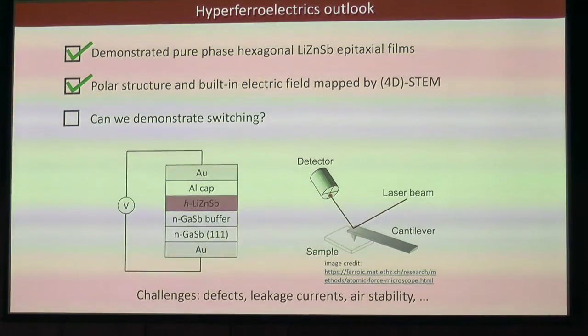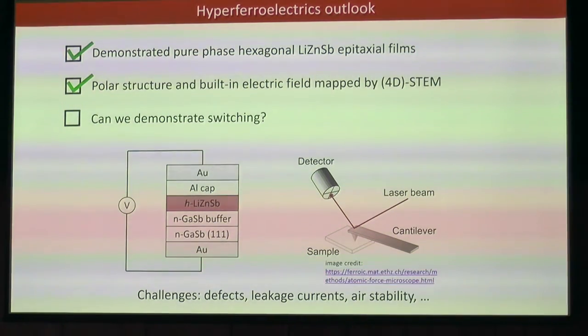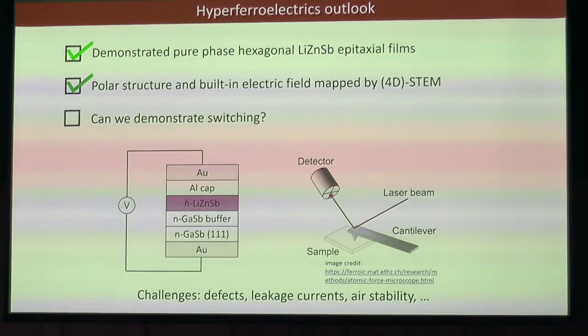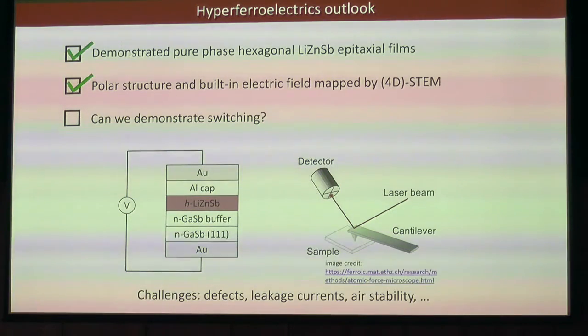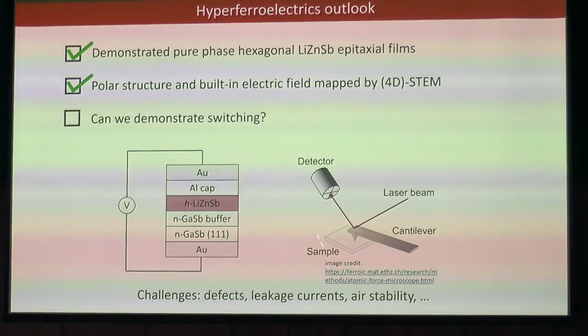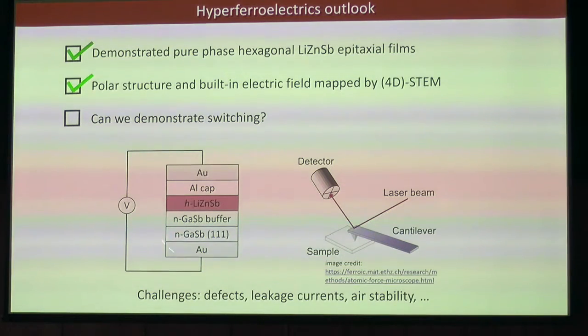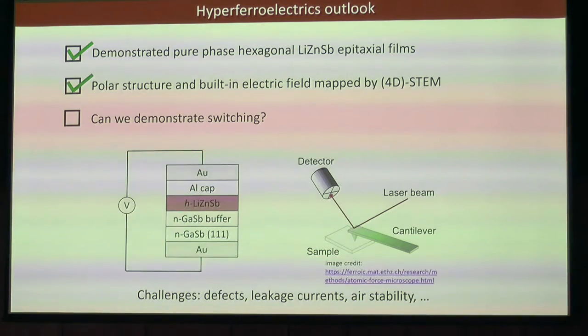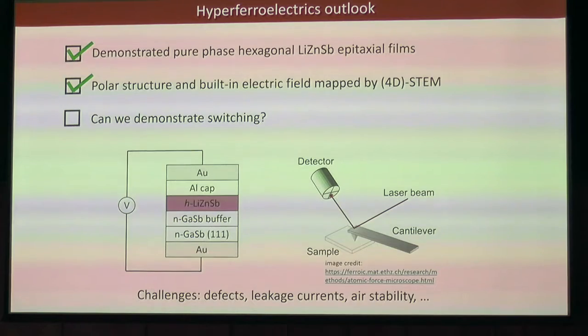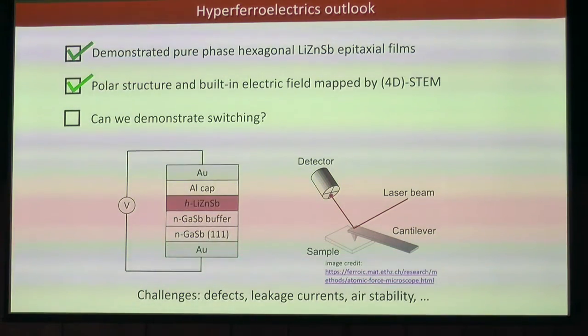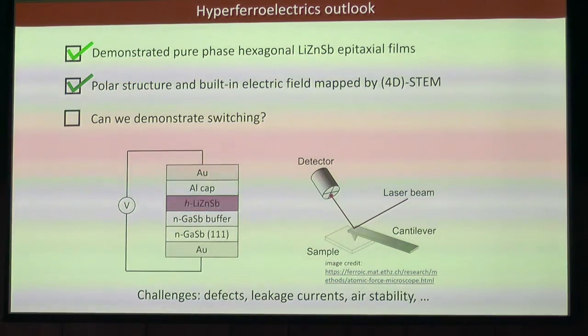I'll say one big challenge here is that because we've got lithium and zinc, and this is not an oxide, these materials are very air unstable. So I think this is going to be very challenging. Maybe we can get to here. I don't have a good sense of how large the leakage currents are going to be. So big caveats, but we're at least getting somewhere.